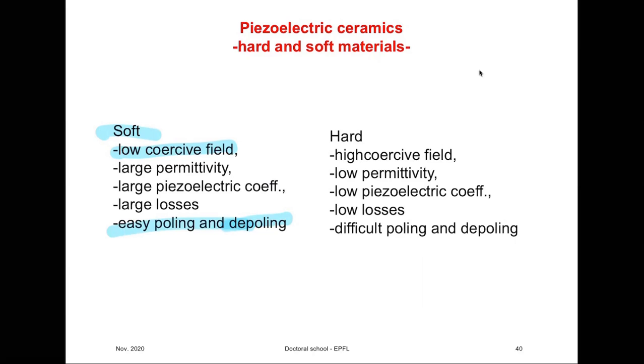Why should pressure depolarize a ceramic? Well, in a ceramic, once it is polarized, most of the domain walls that are left are ferroelastic. Ferroelastic walls are very sensitive to external pressure, so they can reorient. And since pressure is centrosymmetric, that means that you cannot make it more poled. You can only depole it. Well, this is a little bit tricky statement, but if you have a polarization like this and you apply pressure on it, it will do something like that. And that means that with respect to this phase here, the material would be depoled.